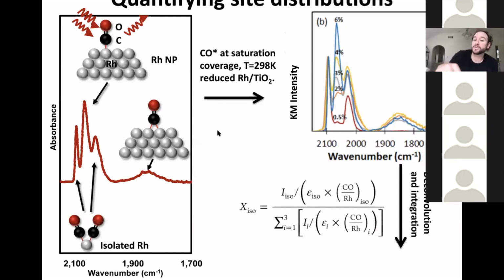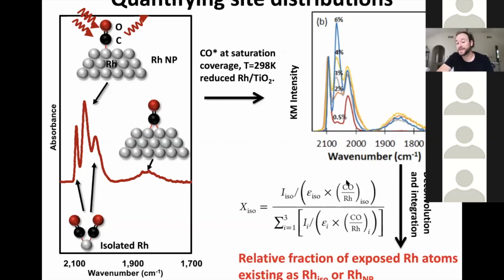Then what we can do is peak-deconvolute these four different features and integrate their areas. We can normalize their areas by the relative extinction coefficients of each of these stretches. Then we can further normalize by the number of COs to rhodium in each of these bonding configurations. Here you have 2, here you have 1 per 2 rhodium atoms, and here you have 1 per 1. Through doing this, you can extract the relative fraction of exposed rhodium atoms existing as isolated species or nanoparticles.